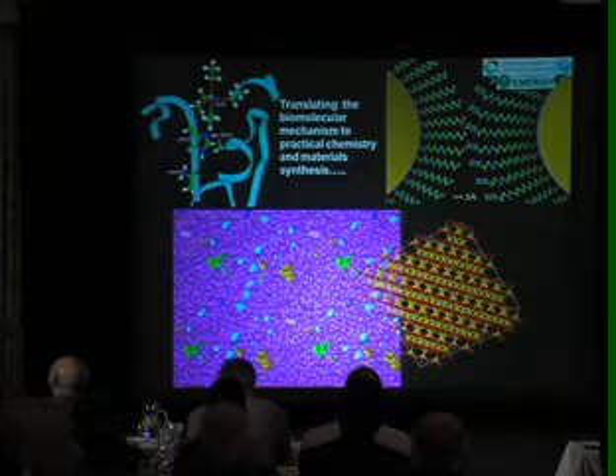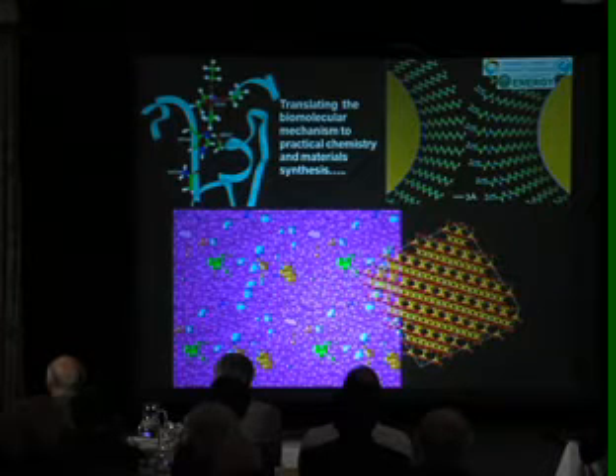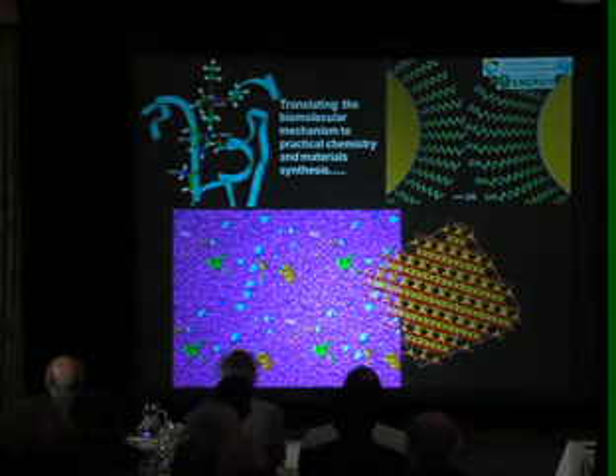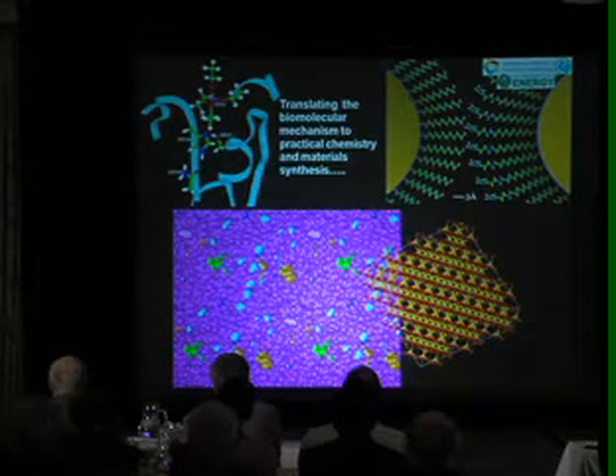And the way in which this protein with specific functional groups on the surface serves as a template to guide the assembly of the nanocrystals of not only silica, but also various semiconductors that we found could also be made catalytically. To gain a better understanding of this mechanism, we made biomimetic mimics of the catalytic site here, showing that if we incorporate the same functional groups, chemical groups that we identified by genetic engineering as essential for the catalytic formation of the silica on gold nanoparticles, we found that it is indeed the collaboration between these chemical groups that is all that's required for the catalysis.